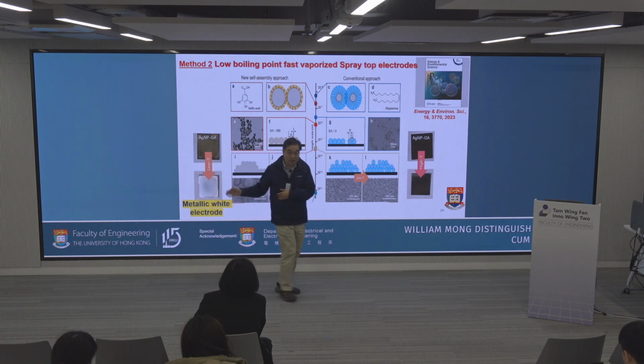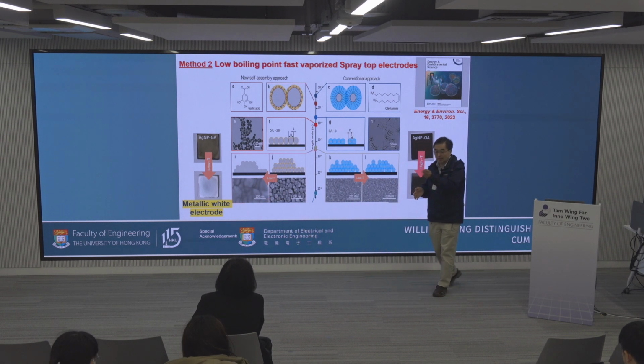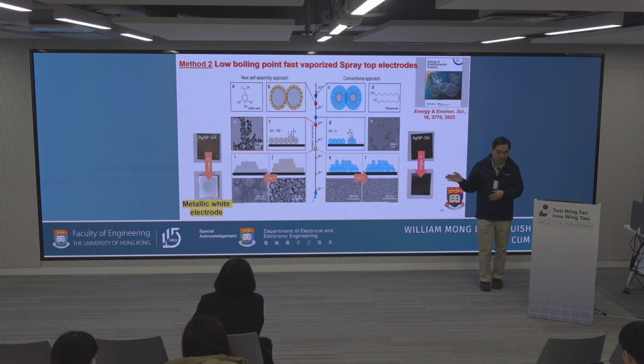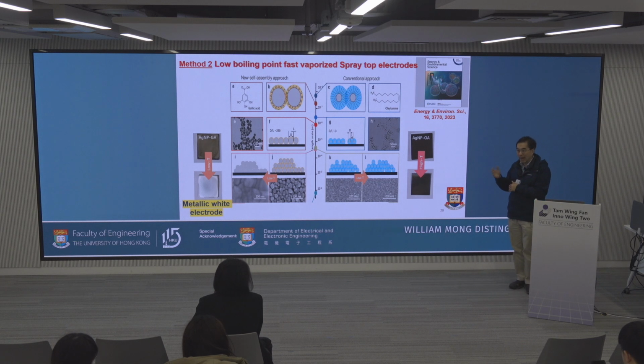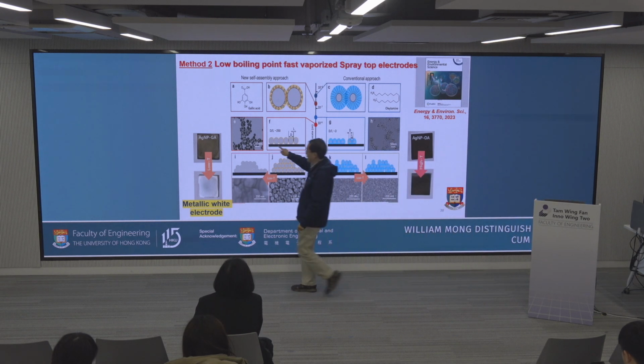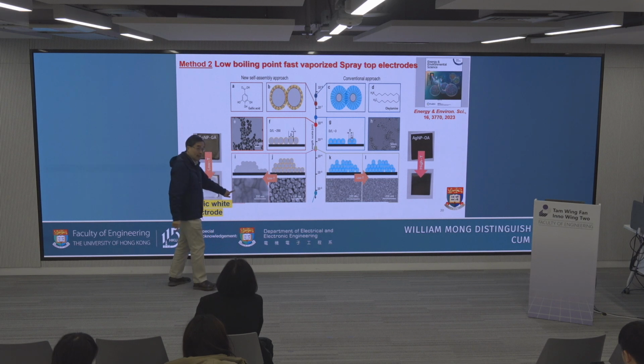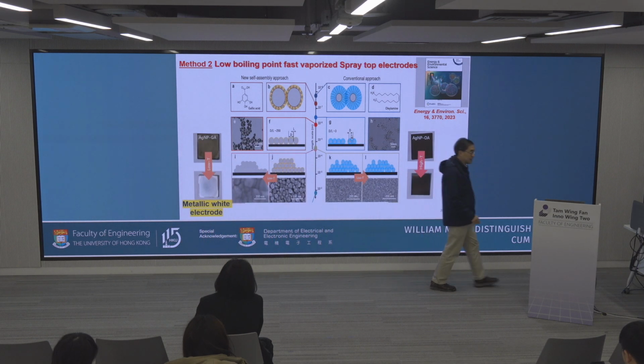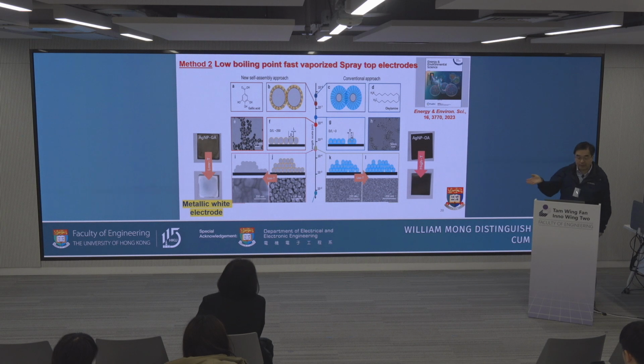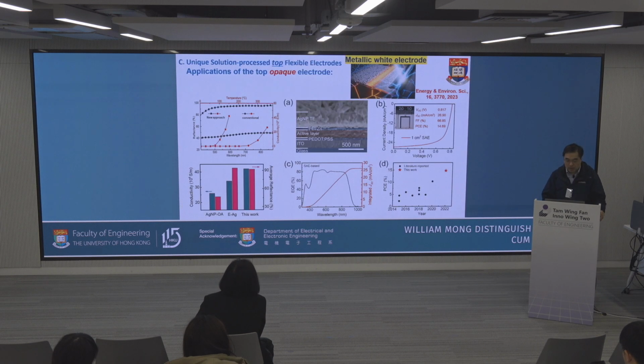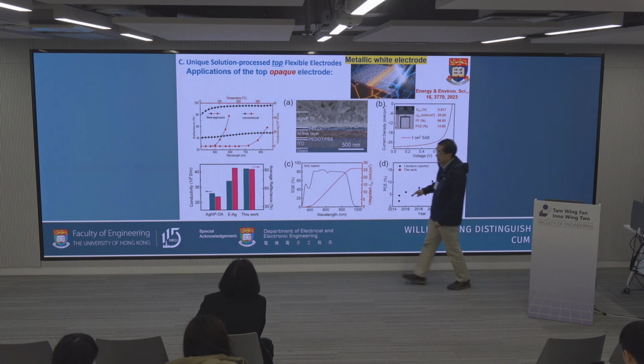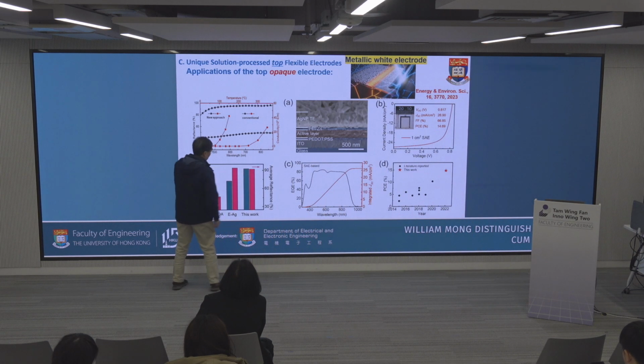This is good for solar cells because if you cannot fully absorb the first round of light, it totally reflects back for a second trip, so all the light can be absorbed again by your PV active layer. For an LED, as a back electrode, it can reflect all the light for emission from the top region. You can see we start with nanocrystals or nanoparticles, and at the end they form grains, as we find in an evaporated electrode. If we evaporate silver and look at it in SEM, they are grains.